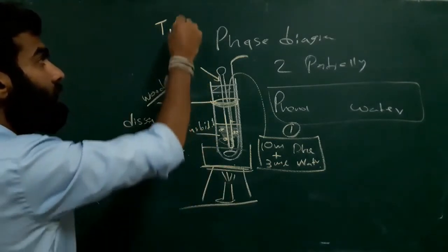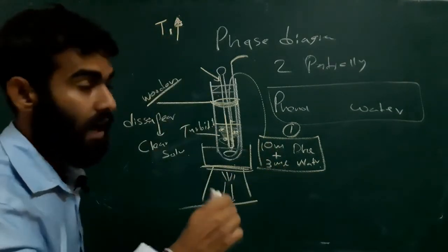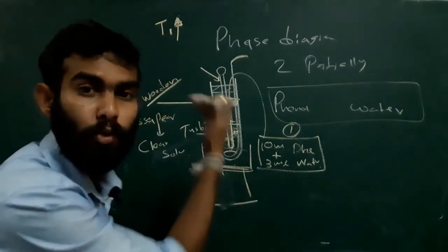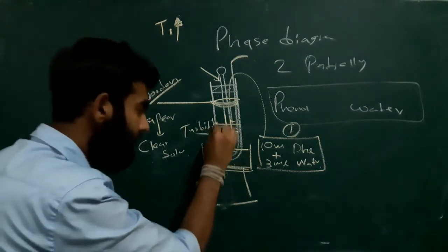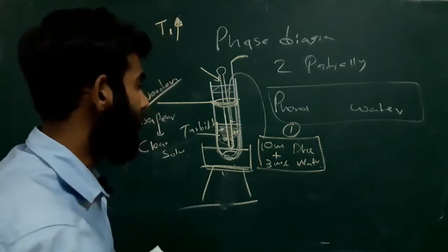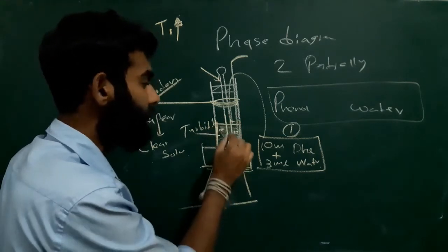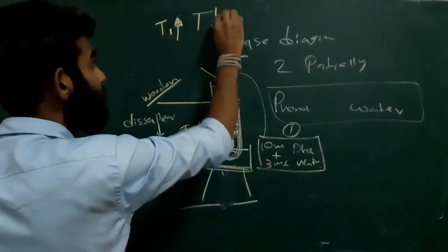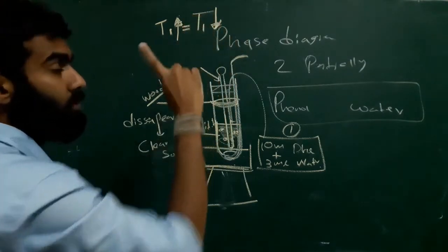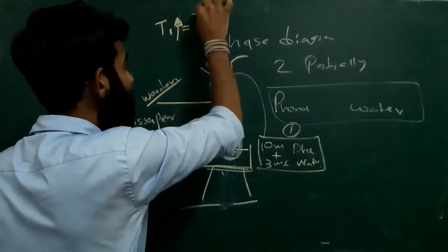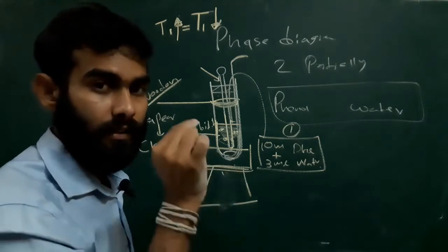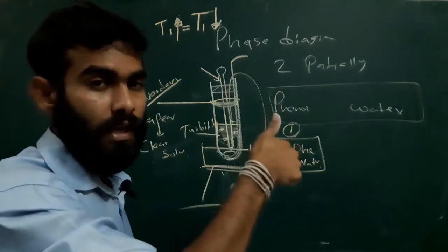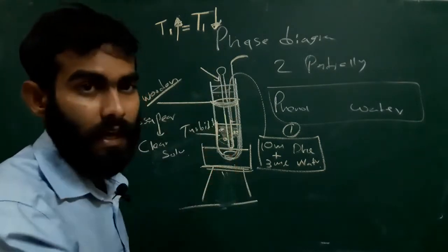When we are heating and increasing the temperature, we can read T1. After reading this temperature, we will remove the Bunsen flame and allow the water bath to cool. Because of this cooling, the boiling tube will also cool. At that time, again we can see the turbidity reappear. That temperature when cooling — turbidity reappears — should be the same as T1, because at that particular temperature the solution transitions between clear and turbid.